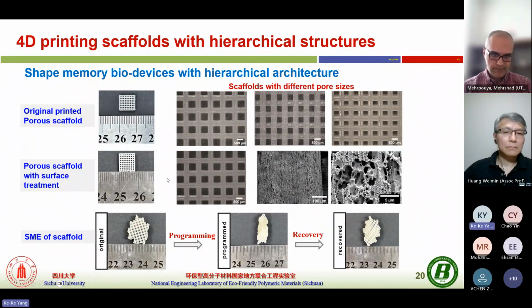Then we print by FDM, and we can print the original porous scaffold, and then we put this scaffold in alkaline solution to accelerate its degradation, and we find the surface will show microscale pores.